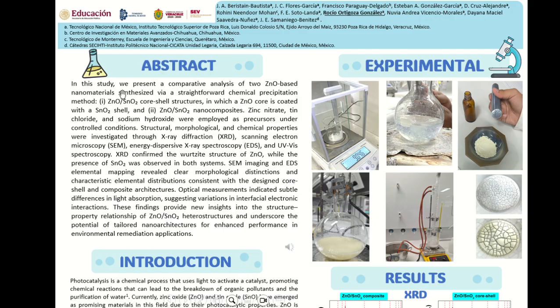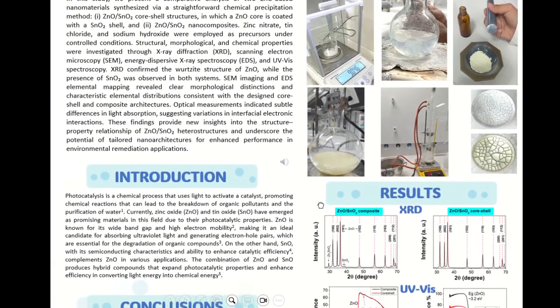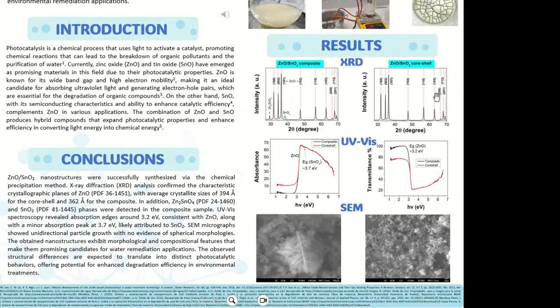In this study, we present a comparative analysis of two zinc oxide-based nanomaterials synthesized via a straightforward chemical precipitation method: zinc oxide with tin oxide core shell structures, in which a zinc oxide core is coated with a tin oxide shell, and zinc oxide with tin oxide nanocomposites. Zinc nitrate, tin chloride, and sodium hydroxide were employed as precursors under controlled conditions. Structural, morphological, and chemical properties were investigated through X-ray diffraction, scanning electron microscopy, energy dispersive X-ray spectroscopy, and UV-vis spectroscopy.